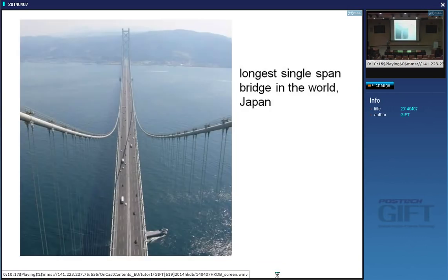And this is another object that I visited. It's the longest single-span bridge in the world. It goes across 2 kilometers with the supports being 2 kilometers apart. And it's in an earthquake zone, just like Taipei 101 is in an earthquake zone. This is in a severe earthquake zone, Japan. And these are cables holding that suspension bridge. The cables are bigger than this wide. I've got another picture showing that. Obviously there are many, many cables inside that. And the atmosphere inside the cable is maintained as inert so that you don't get corrosion. And it's able to span 2 kilometers without any support underneath, because the ropes are extremely strong, something of the order of 3 gigapascals in strength.